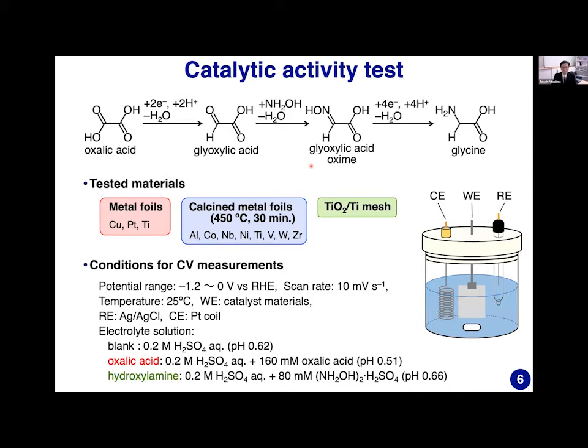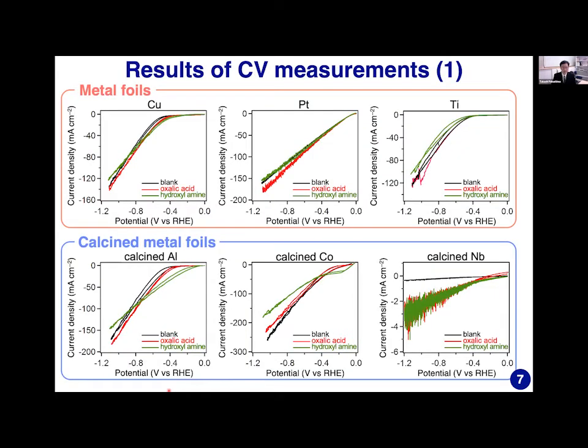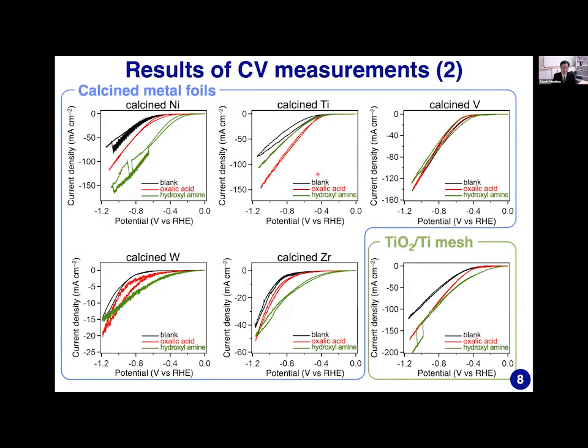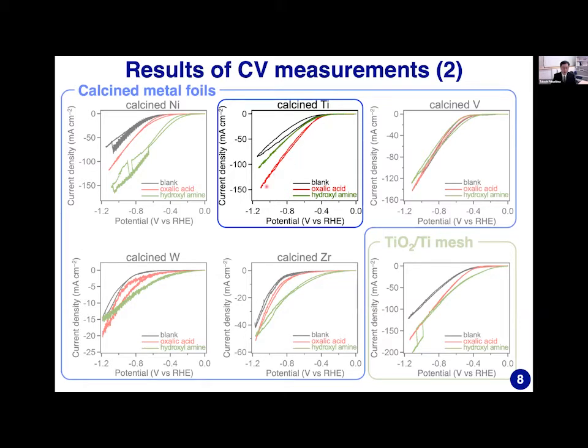Thus, we have to find a catalyst which has higher activity for oxalic acid reduction than that for hydroxylamine reduction. We tested metal foil, calcined metal foil, and titanium oxide titanium mesh. We measured CVs of these materials in the presence and absence of oxalic acid and hydroxylamine. These two slides show the result of CV measurement. It can be seen that only calcined titanium foil exhibits higher catalytic activity for oxalic acid reduction than that for hydroxylamine reduction, while the other materials, including titanium oxide titanium mesh, have higher activity for hydroxylamine reduction.